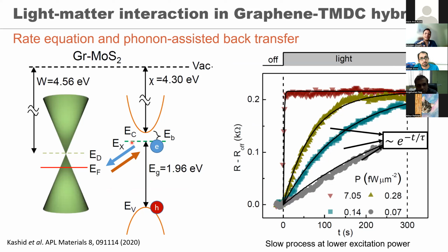And as a matter of fact, it recovers a little bit. This is the question from Ashish, which I was trying to answer, and we have the data in this paper itself, as a function of temperature. We found that the photoluminescence slowly starts recovering at lower temperature, where the excitonic recombination time scale becomes smaller, and hence there is a competition between the charge transfer time and the excitonic recombination time, which become comparable. That's when you start seeing a slight recovery of the photoluminescence. But at room temperature, all flat, no photoluminescence.